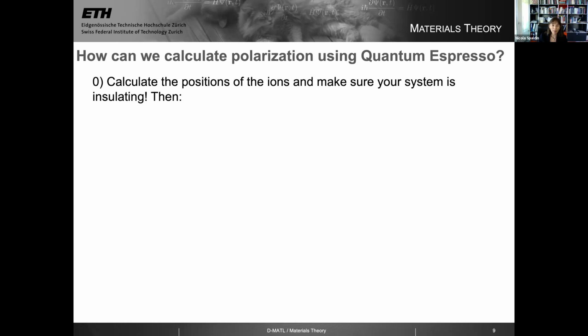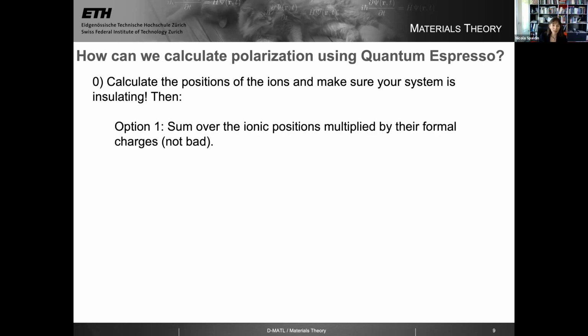Once you have that, then you have a few choices. The first option is you can do just what we've been doing with these cartoons. You can take all of the ionic positions and multiply the position of the ion by the formal charge and add them up. So you can work out the dipole moment per unit volume just by simply saying, okay, calcium is +2, oxygen is -2, lithium +1, and so on. Sum over those formal charges and multiply by the positions.